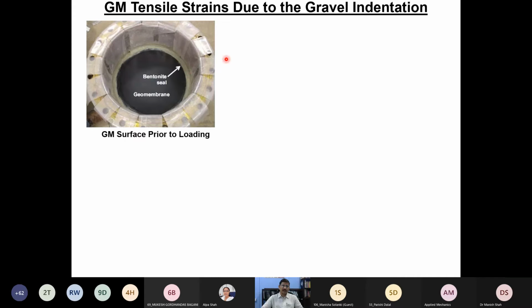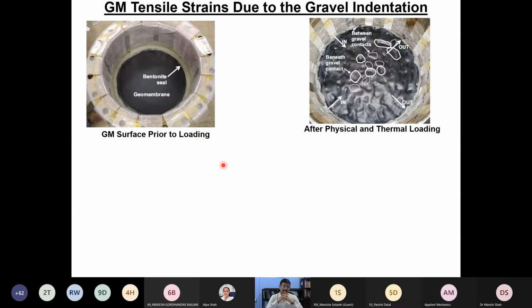After placing that, we place a rubber membrane, the bladder, and the bladder is pushed down by inflating it in the other direction. After testing this condition, the smooth geomembrane was subjected to severe indentation. When we tested the material at 35 degrees centigrade, we applied around 250 kilopascal loading, which is similar to around 20 meters height of waste, not more than that. And only after 2 months, the membrane is severely indented, even after placing the protection geotextile.